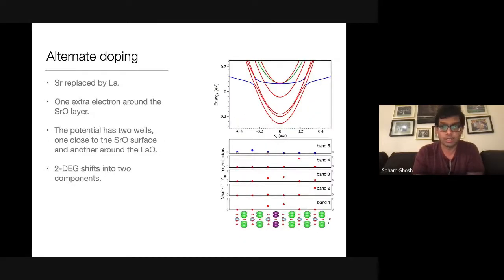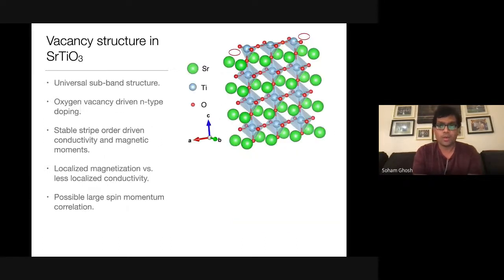For example, you can alternately replace strontium by lanthanum, and you'll see that the electrons start coming towards the lanthanum. So you'll shift the electron gas into two components. So in a way, you could call this interface and surface electron engineering. So you choose what you want to dope with, and the electron reacts accordingly. What you can also do is look at whether there is any vacancy when you do this interface engineering. And it turns out that there is not just a vacancy, there is a very specific type of vacancy. What the vacancy looks like is a stripe.